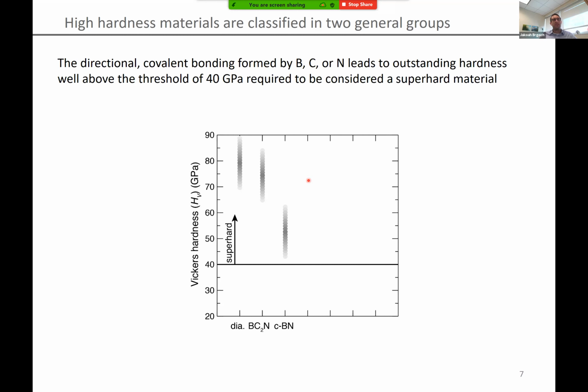Now, the hardness of these phases arises from the fact that you have short directional covalent bonds by these main group elements. Take, for example, diamond: you have these sp3 hybridized orbitals that point perfectly at other sp3 hybridized orbitals, and they form these very strong, short covalent interactions. That's what gives rise to the high hardness in something like diamond.